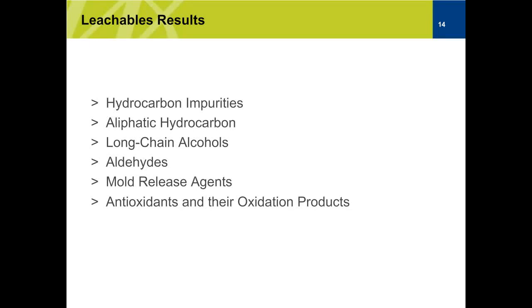So really, all of these additives leach into solutions, and the way you look for them is, we find there's going to be a lot of hydrocarbon impurities, aliphatics, hydrocarbons, long chain alcohols, aldehydes, mold release agents. It's a huge mess. They leach out very easily, even in the presence of water. And then also antioxidants and their oxidation products. So these are all the different impurities that you might see in your experiment if you're not using high quality, high purity labware products.